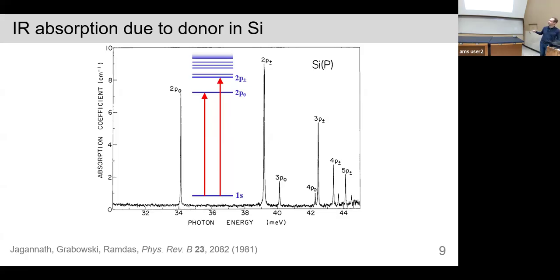And so this is a beautiful spectrum at low temperature where you see the 2p0 and 2p plus minus, 3p0, 3p plus minus. What the plus and minus is that there is some splitting because this thing is in a solid and not in vacuum. So those do have some splitting, and it's related to the different band curvatures in this direction or that direction for the conduction band. But other than that splitting, it's essentially a 1s to 2p transition, and you see those as sharp peaks, 1s to 3p, 4p, and so on, and a little continuum absorption.